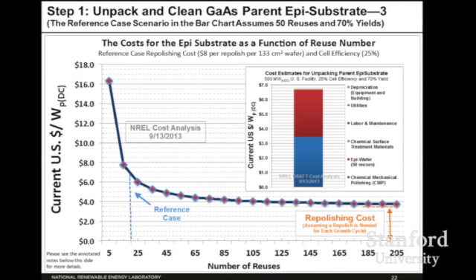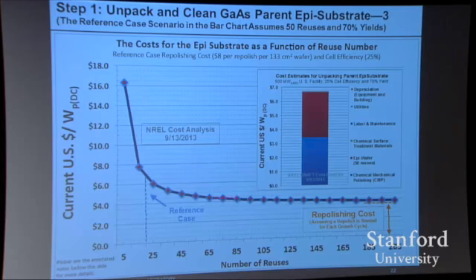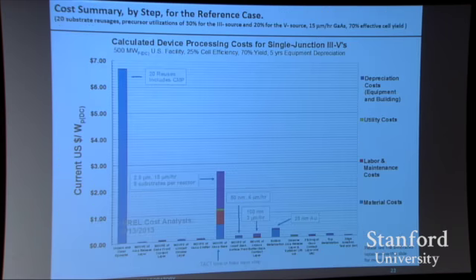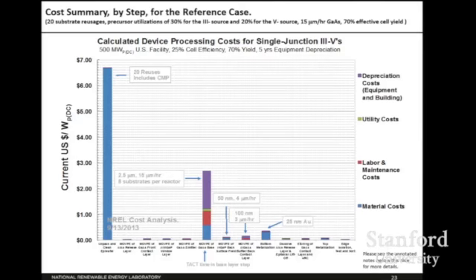With lots of reuses, you get that to $4 per watt. And then in their analysis, it saturates at $4 per watt because they think that's what it's going to cost just to repolish the wafer. And so that's about where you can get. Now I skip all the way to the end of their analysis. I'm not going to show you a slide for every single one of these steps. But you see that the 3 big ones are the wafer, and then right here, this is the deposition of the gallium arsenide. That comes in at about $2.50 per watt. And then there's a gold electrode that comes in at about 30 cents per watt.